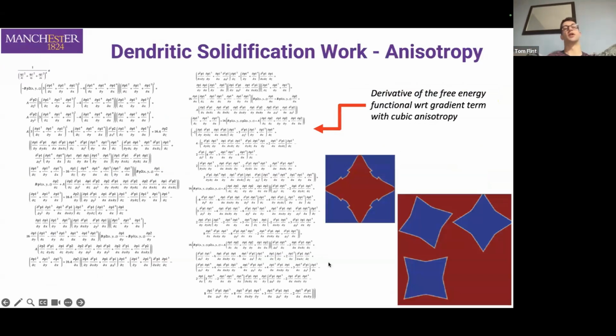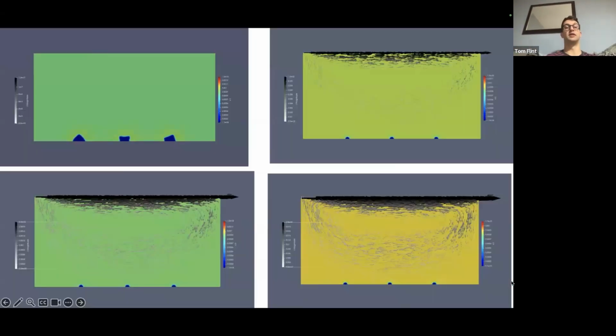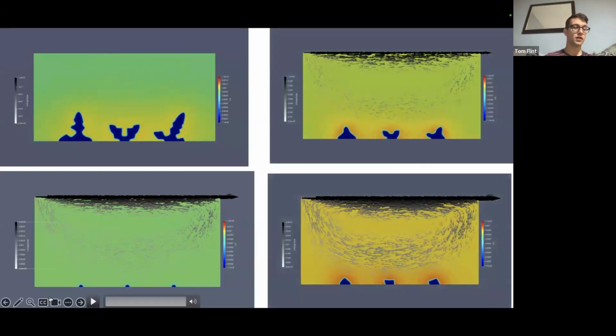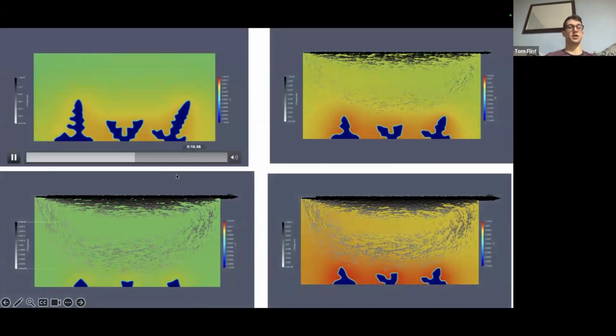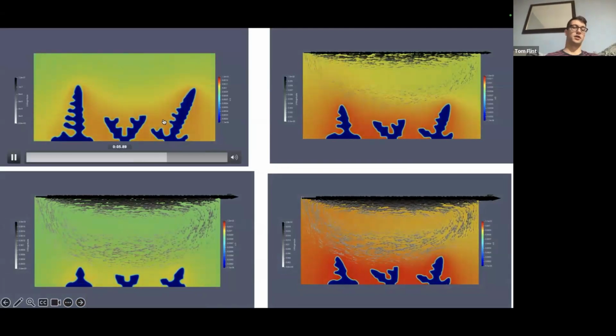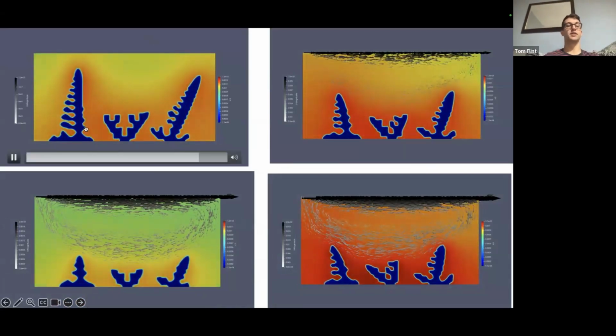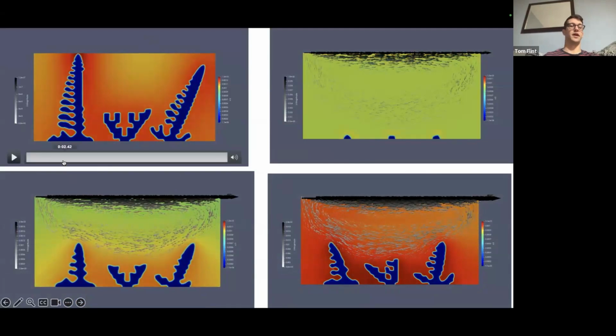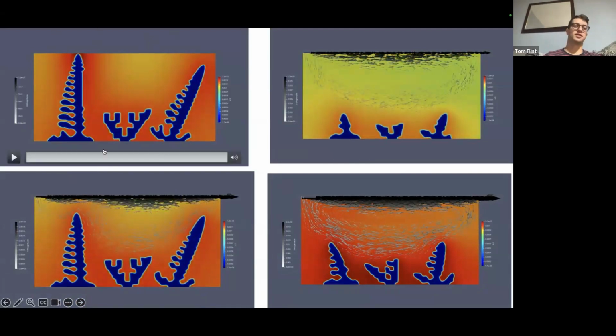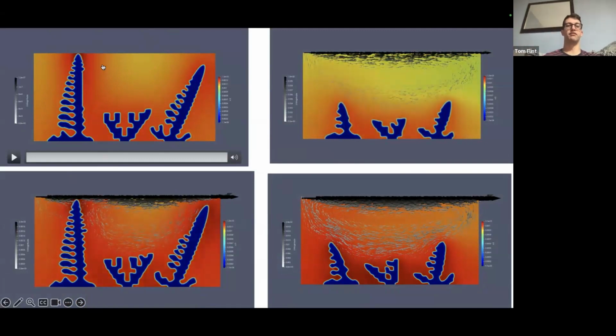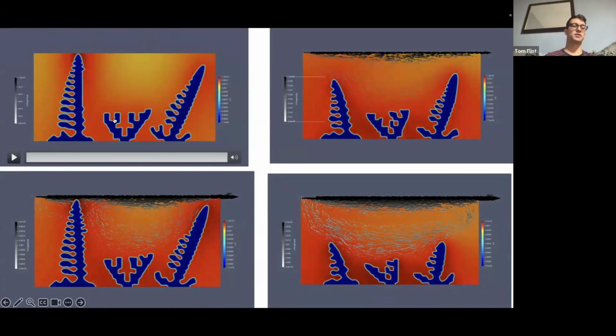So we have this in our code, which again is going to be open source probably by Christmas, I would have thought. So you can predict these, you can run this code, and here are some examples of our code in action. So what we have here is some crystals, some solid seeds, I guess, on the boundary, and then they're allowed to grow. In this case, in the top left, we have no applied velocity field, and that's the other thing. We have the flow through the dendrites in our code, in our mathematical framework.